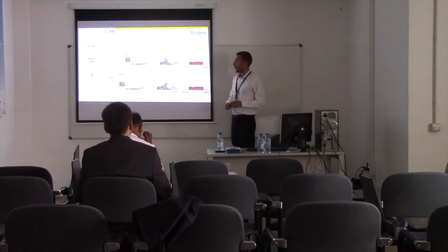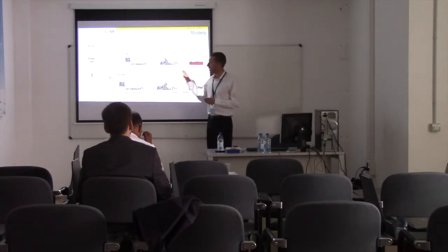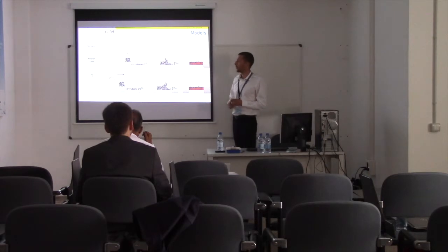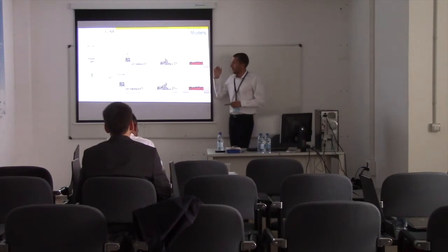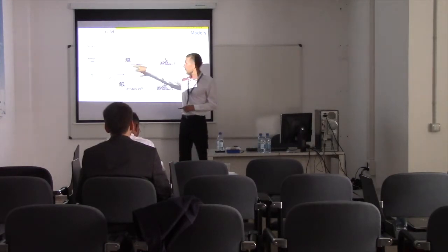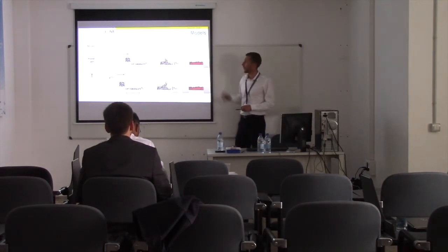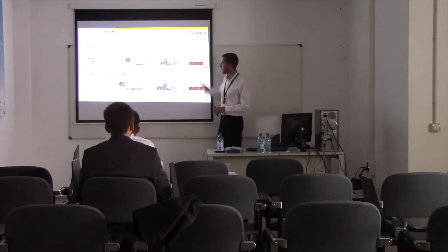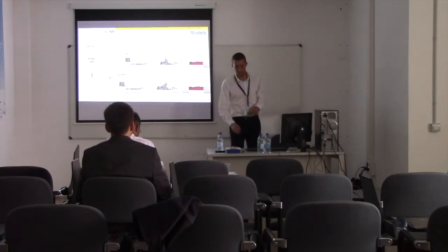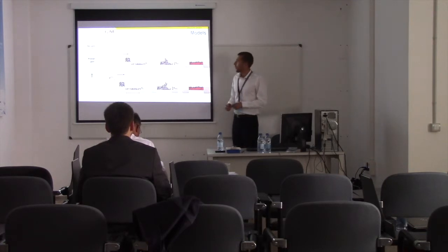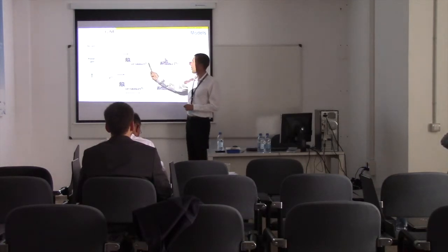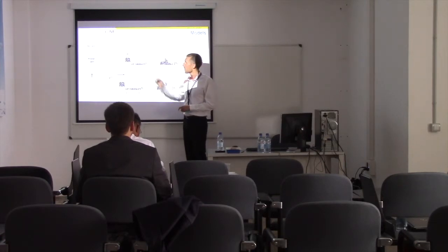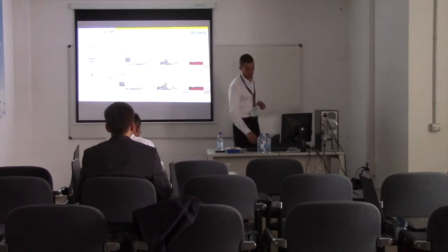So here you can see two drawings. We try to make two recoater systems, a blade and a roller, which can be seen on different additive manufacturing machines. We have our powder bed volume, which will be spread on the build platform, layer by layer, so 50 micron by 50 micron. We will deposit this powder bed layer and do some analysis for the blade and the roller. The main variables we started with were the powder bed thickness and the recoater speed.